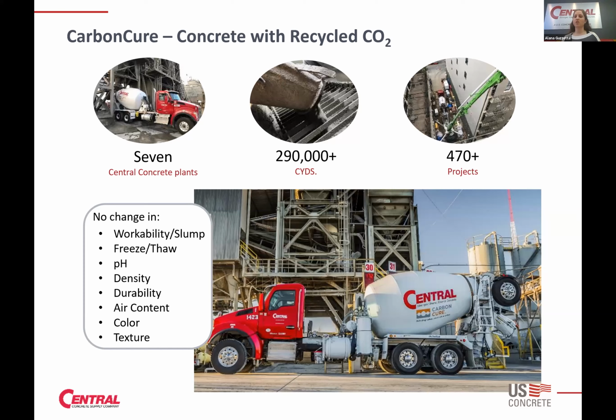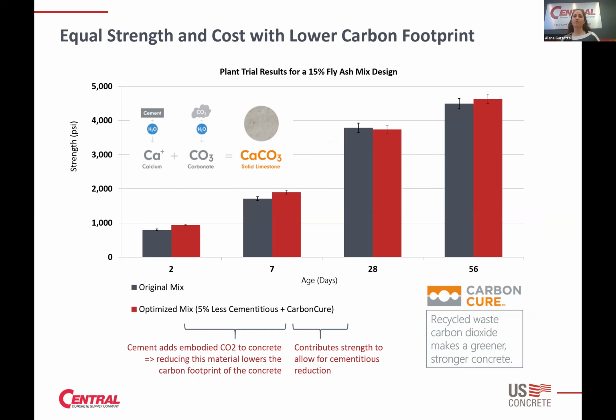Great benefits to this are that it's not going to change the appearance of the concrete to the contractor. So the workability, and everything that you see as a fresh property, is going to stay the same. The way it works is when you inject the CO2 into the concrete mix, it turns into carbonic acid and reacts with calcium ions from the cement and forms very small calcium carbonate. That's what Michael talked about as limestone. So these very nano-sized limestone particles are going to help promote the hydration to react a little more early on and, at the right dosage, give a strength boost to the concrete. And with a strength boost, you have potential to further reduce the amount of cement that's in the mix.